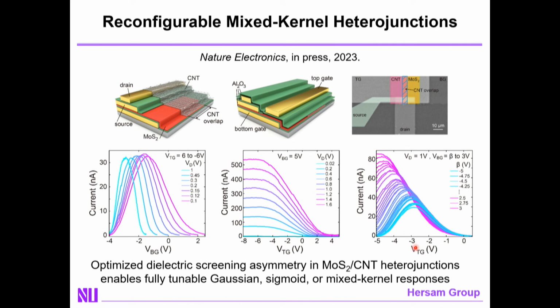You can go one step farther. This is work that's just about to be published, where now what we're going to do is intentionally vary the nanotube density. That will allow us to more exquisitely tune the asymmetry and the dielectric screening across the mixed dimensional heterojunction. That allows you to not only get exquisite tunability over the Gaussian response, but also achieve a sigmoidal response or a linear combination of the two.